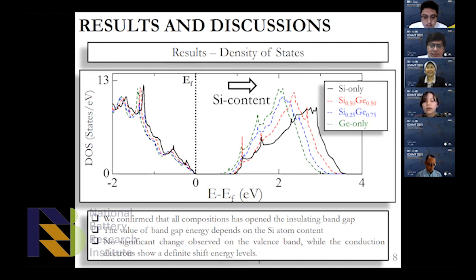And the gap value for the silicon 0.5 germanium 0.5 alloy is calculated to be 0.89 electron volt, while with the decrease of silicon composition, the silicon 0.25 germanium 0.75 alloy is 0.75 electron volt. Okay, so all of the calculated band gap values are still lower compared to the real experiment, about around 50%. One possible reason for this is that the SCAN functional still underestimates the interaction between atoms, which reduces the gap energy.